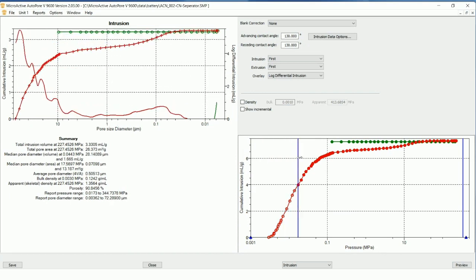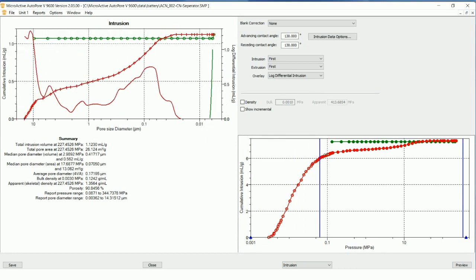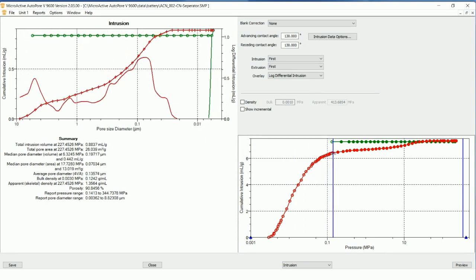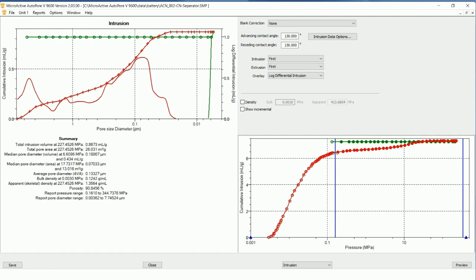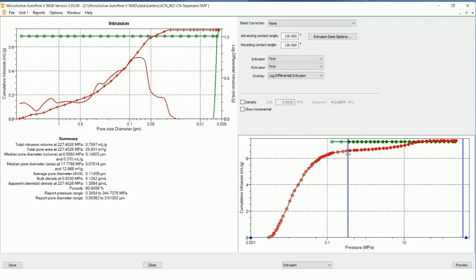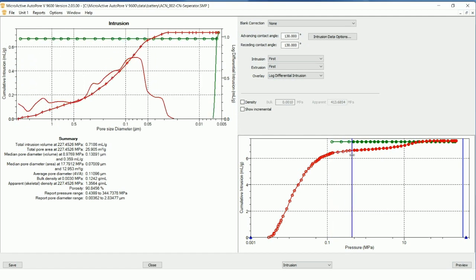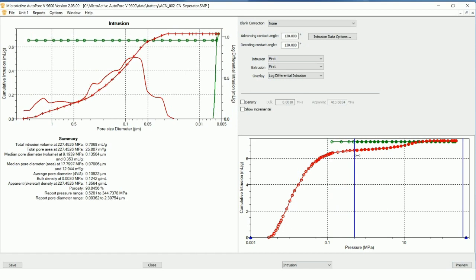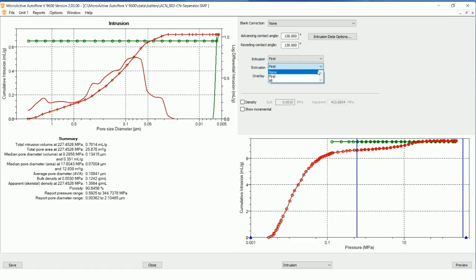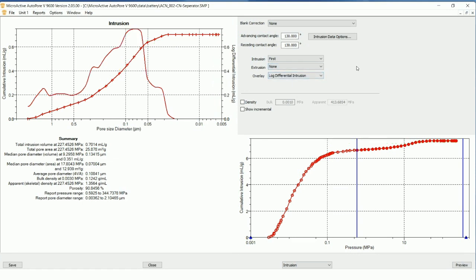And if I take this over to where, if you look on this lower right-hand graph, it's showing pressure in megapascals. If I take this over to about 1/2 megapascal, which is going to correspond to a pore size of about 2 micrometers. So, and let's just take off the extrusion here so we see a little better. So here we see what is probably the pore size distribution actually of the pores being filled. We've removed that interstitial filling.